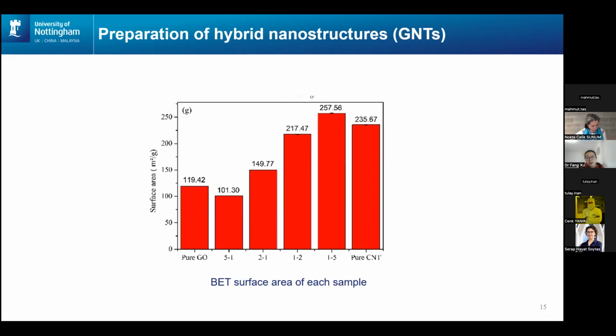Okay, so when we do this experiment, we keep the mass the same. For example, we use 10 milligrams in total weight, so we use either 10 milligrams of graphene oxide at the left end or 10 milligrams of carbon nanotube at the right end. So we can see actually carbon nanotube does have a larger surface area than graphene oxide if we prepare them in this method. So we have confirmed that mixing them does help with surface area, does help with dispersion, okay?